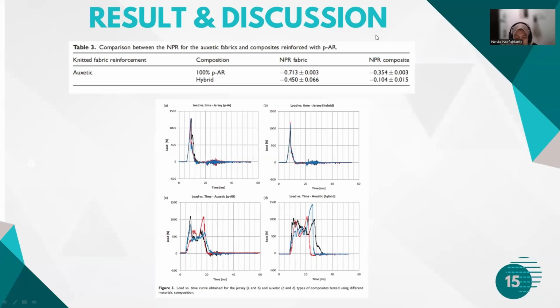Results and discussion. The results obtained show that although the auxetic behavior decreases, it is maintained in the produced composite, from minus 0.713 in the fabric to minus 0.354 in the composite. In addition, the use of high stiffness filaments such as para-aramid in the production of the auxetic weft-knit fabrics resulted in a strong improvement of the NPR in the composite when compared to hybrid materials. The representative curves of the composite are shown in Figure 3.